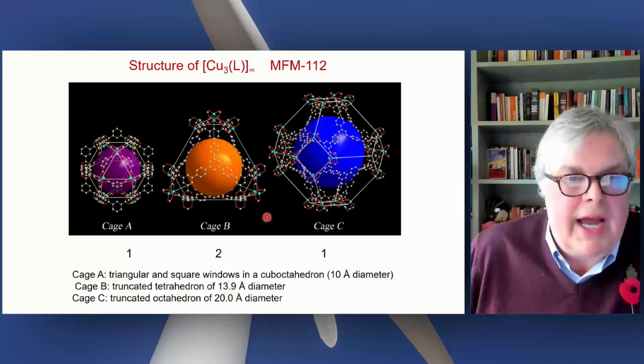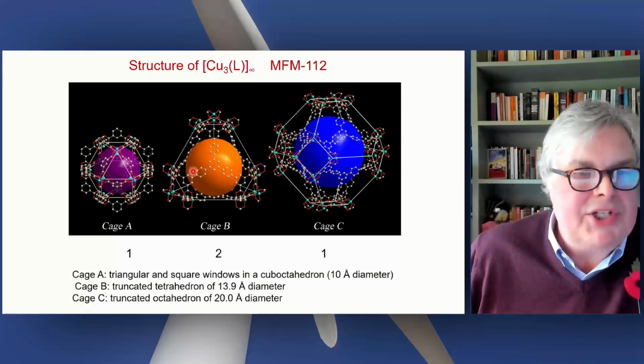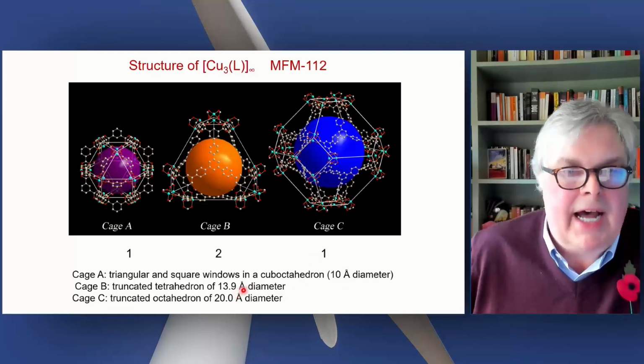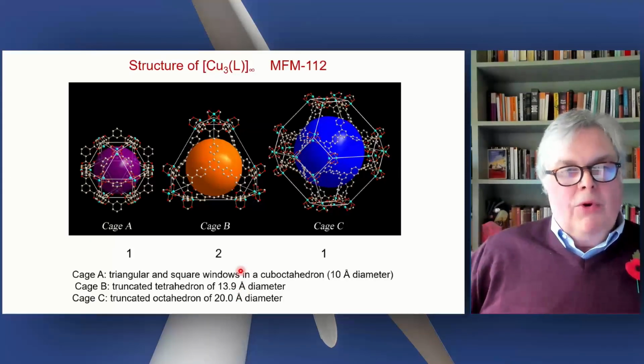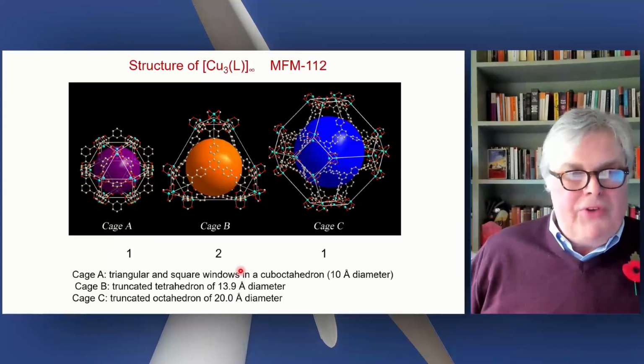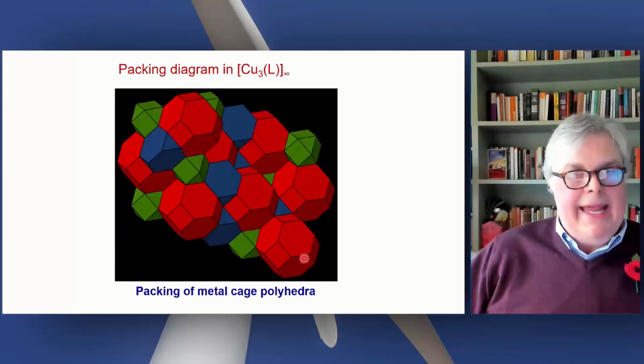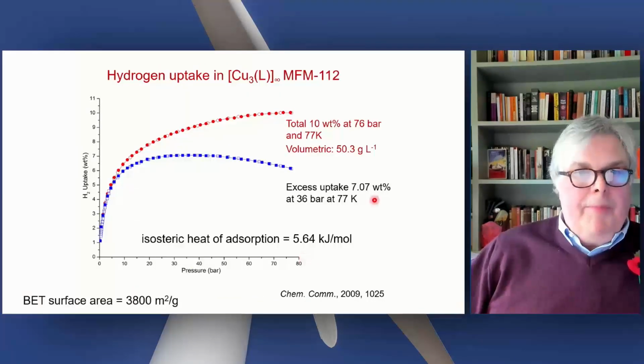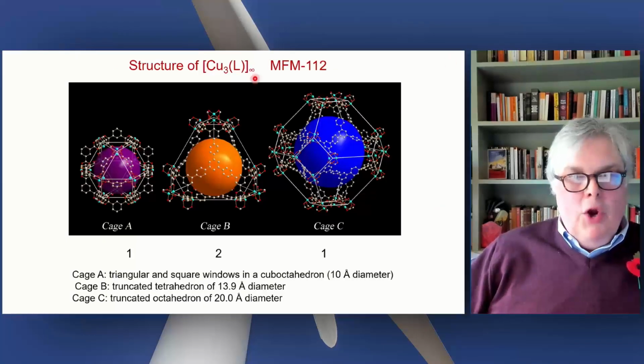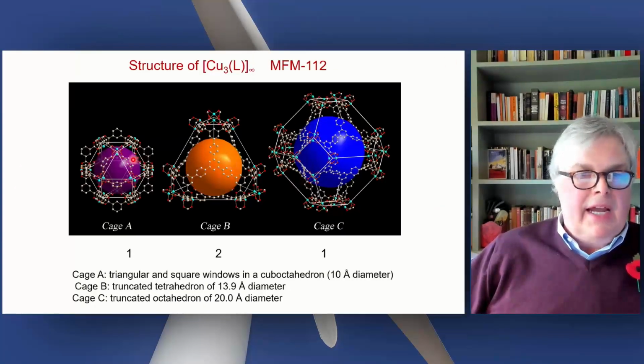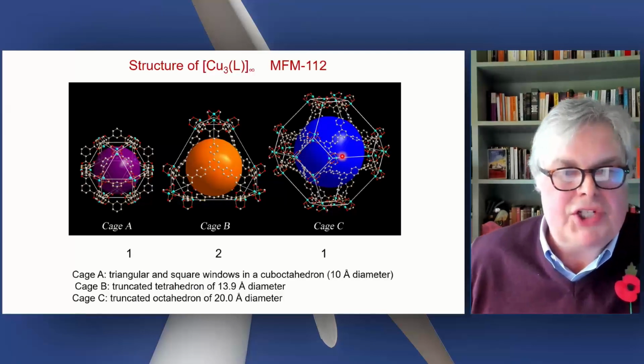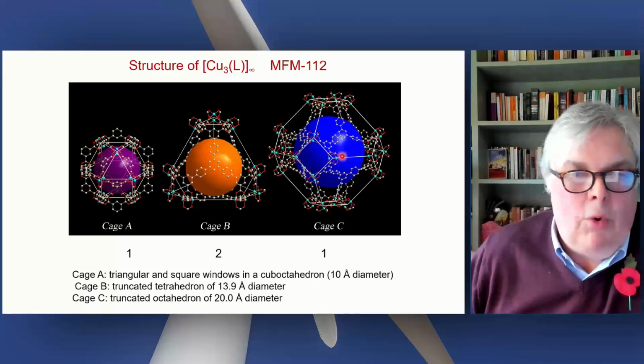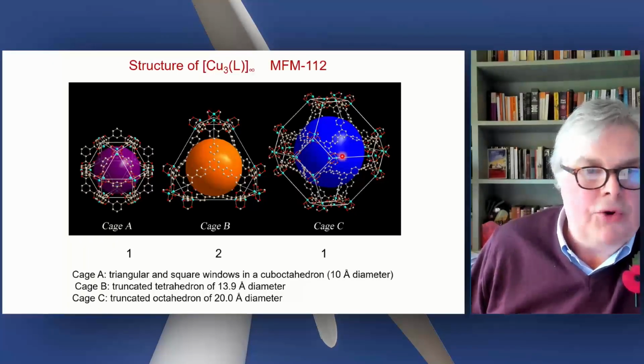The overall structure actually comprises 3 cages, cage A, B, C. These are of different diameters, 10, 14, and 20 angstroms in diameter. And so you can view the metal organic framework as a series of fused cages, which I illustrate here. The material is prepared with solvent molecules inside these cages, inside the pores, which you then remove either via solvent exchange and heating, or solvent exchange and heating under vacuum.